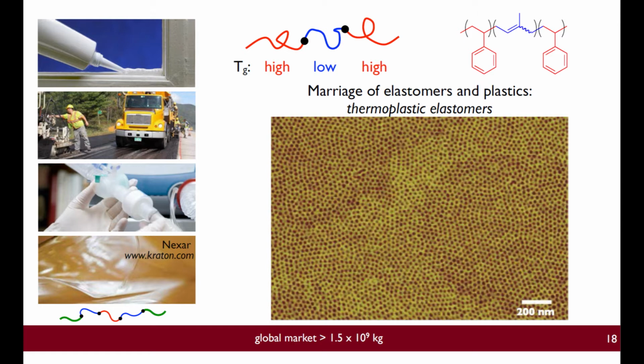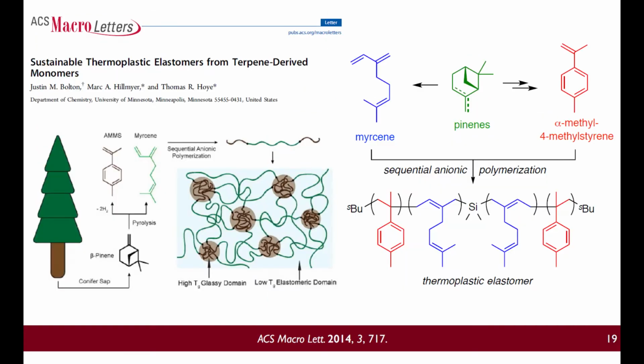Moreover, they're quite interesting because they can self-assemble into nanostructures like I've shown in this AFM image, but it is this microphase separation that lends itself to these amazing properties of these thermoplastic elastomers. That is, they can be processed like plastics, but they behave like cross-linked elastomers. We looked into trying to look at modified ways to make thermoplastic elastomers, and this is just a recent example from our work where we showed that you can actually take terpenes, beta-pinene, and beta-pinene can be converted into alpha-methylstyrene or a molecule called myrcene. This is a substituted styrene, and this is a substituted isoprene. It turns out those molecules can be polymerized by anionic polymerization to generate this red-blue-red triblock, also a thermoplastic elastomer, but derived entirely from turpentine.